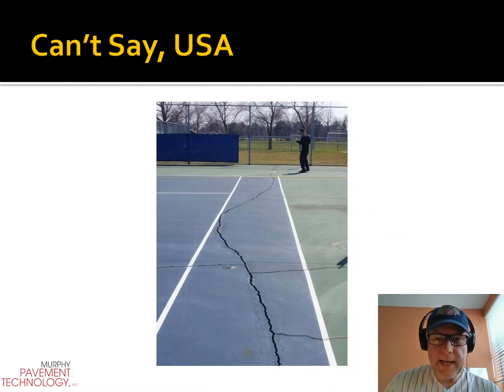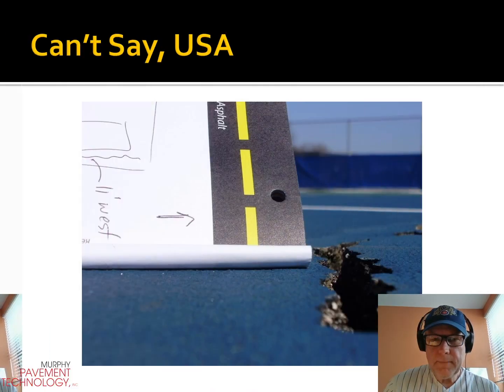This is the asphalt itself, and those are very excessively wide cracks, somewhere in the 1.5 to 2 inch wide cracks. They just absolutely shattered. Moisture got in and started pushing it apart when it froze in the winter months. Upon exploration, we could see how the cracks widened from 1/2 inch to over 1 inch over one winter.